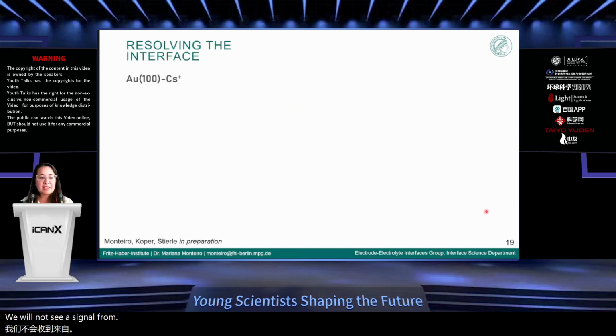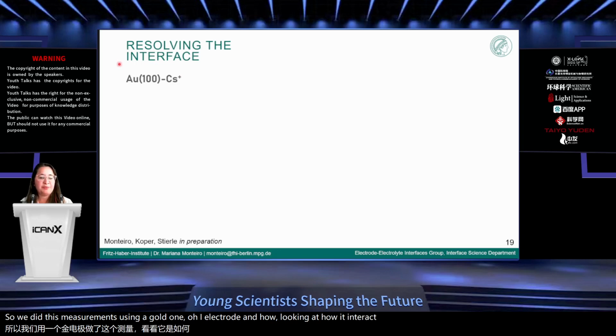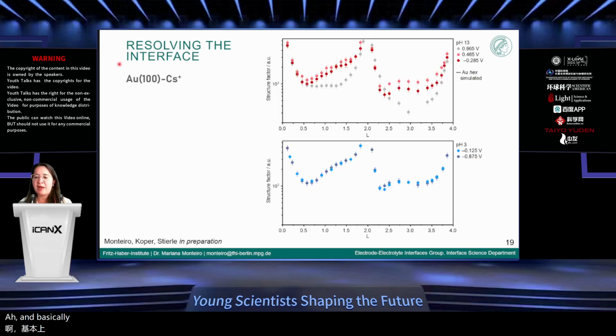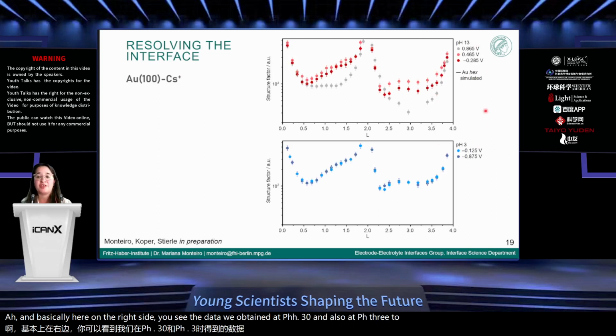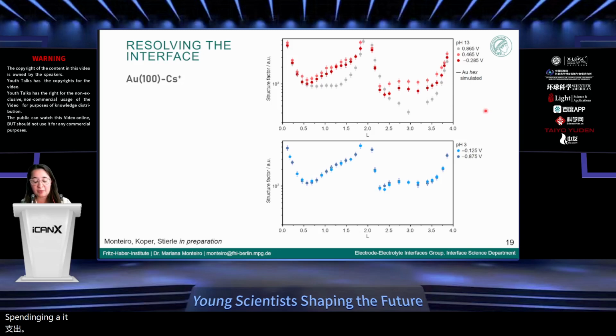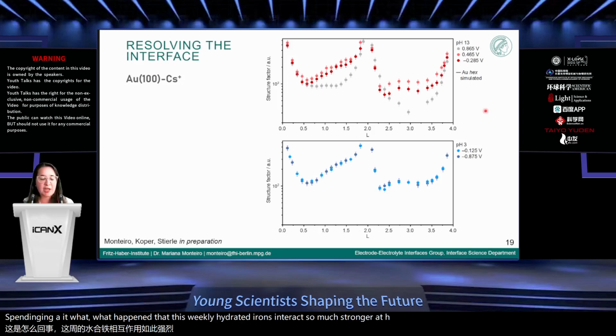So we did these measurements using a gold 100 electrode and looking at how it interacts with cesium. And basically here on the right side, you see the data we obtained at pH 13 and also at pH 3, to try to start understanding what happens that these weakly hydrated ions interact so much stronger at high pH.